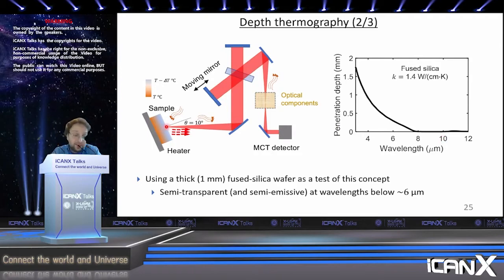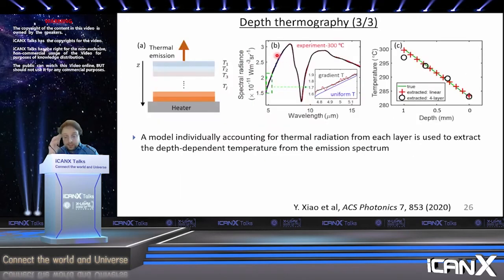The idea here is to figure out what is the surface temperature, what is the temperature 100 microns in, what is the temperature 200 microns in, and so forth, just from a simple thermal emission measurement. And so this is what we did. Here is the basic idea computationally. We can take the sample, which is the same material everywhere, and break it up into many different layers. This is a discretization of the sample. Essentially, we can assume that each one of these layers has a slightly different temperature, and our task here is to figure out what each one of these temperatures is.